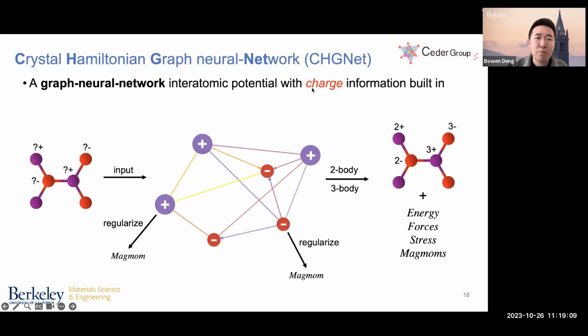So for a summary, the workflow of our model, called Crystal Hamiltonian Graph Neural Network, in short CHGNet, is as follows. A crystal with an unknown charge state is used as input, and we send it to CHGNet, where we use both 2-body message passing layers and 3-body interaction layers to calculate the energy, force, stress, and magmoms of the given crystal. Different from previous machine learning interatomic potentials, we regularize the node-wise features, which represent the atom information, to the magmoms associated with the corresponding sites, such that the atom features are forced to contain information about atomic charge. As a result, mixed valence state ions like manganese 3 and manganese 4 will have a different interaction as represented in the graph neural network, even if they were provided with the same elemental labels.